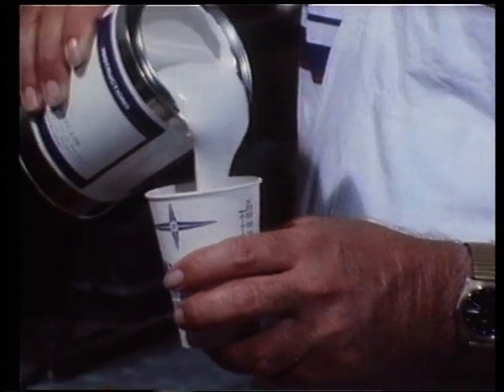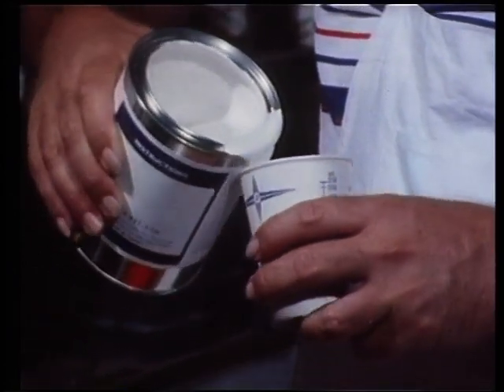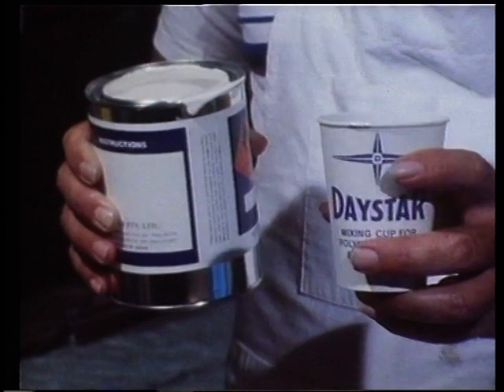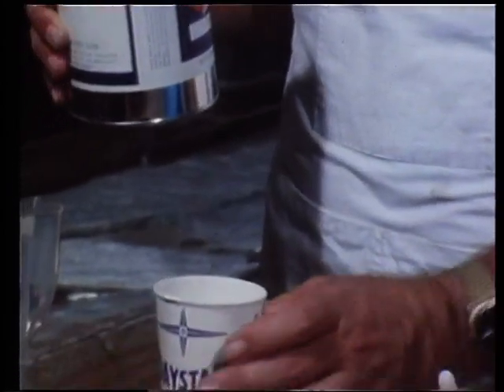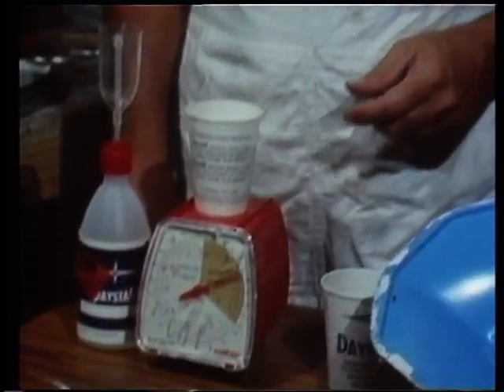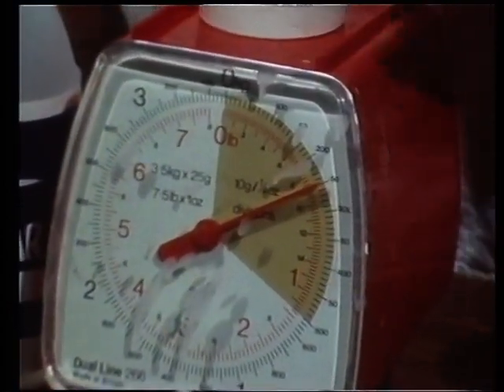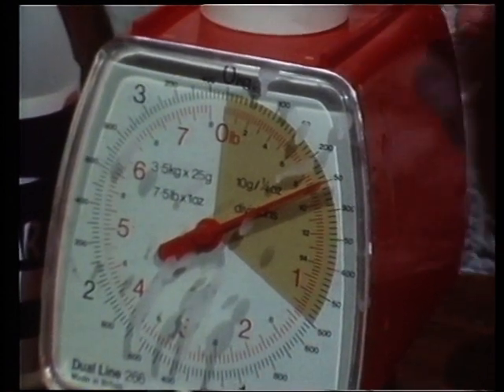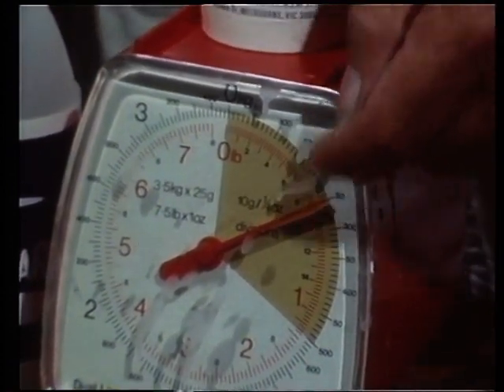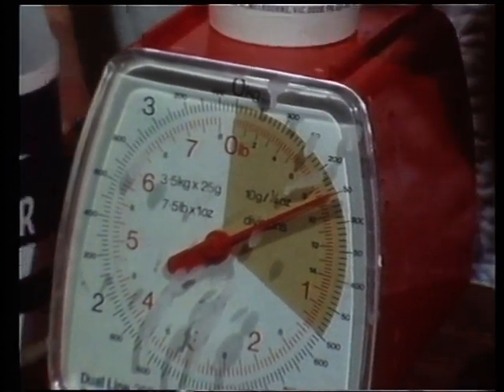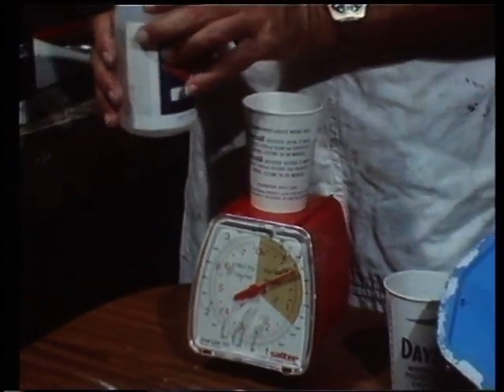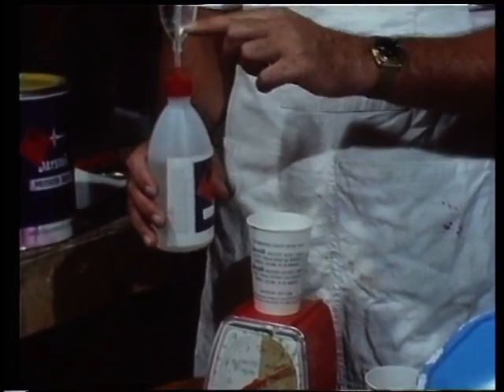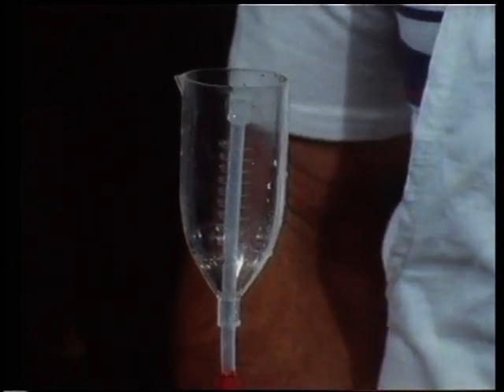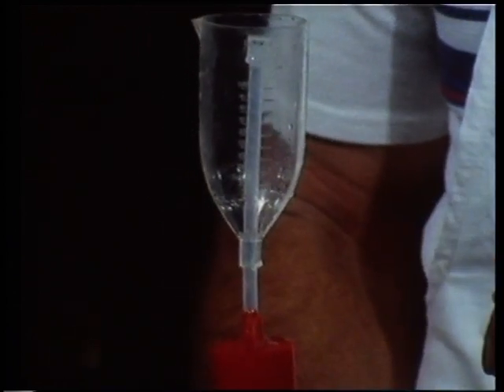I pour the gel coat in there, and that's a pretty basic way of doing it, making sure that I don't go any closer than about 25 millimetres from the top, and I put it on the scale. Now the scale shows 250 grams, and I want 1% of catalyst in that resin to give me an average cure time. Now you can quite easily transpose grams for millilitres, and this catalyst bottle has graduations on the side in 5 millilitre increments starting at 5 millilitres. Now with 250 grams of gel coat in there, I'll want 2.5 millilitres of catalyst.